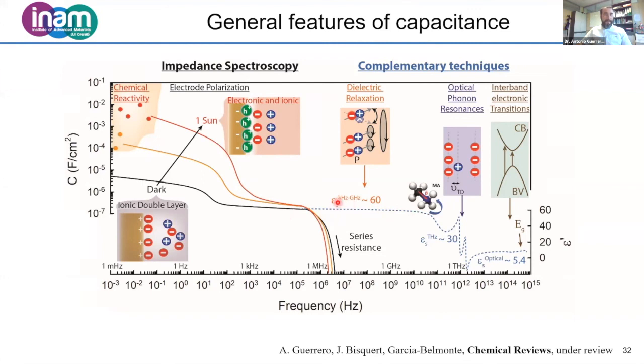Okay, so when we do the impedance spectroscopy measurement in the dark, the high frequency arc that we observe correlates quite well with the measurements obtained using all these other techniques. So this capacitance is related to the permittivity of the perovskite material. So this is a bulk property